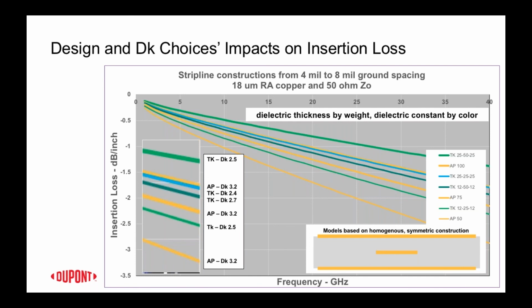as a result of all that. The next line is a potential variation on the Pyralux TK construction that puts us at an even lower dielectric constant than the standard. So at 2.4 dielectric constant, a construction for Pyralux TK that's targeted at 3 mils gives us 6 mil dielectric spacing between the ground planes, and gives us insertion loss that's just about equal to the 4 mil Pyralux AP, or 8 mil ground plane spacing, that it's adjacent to.